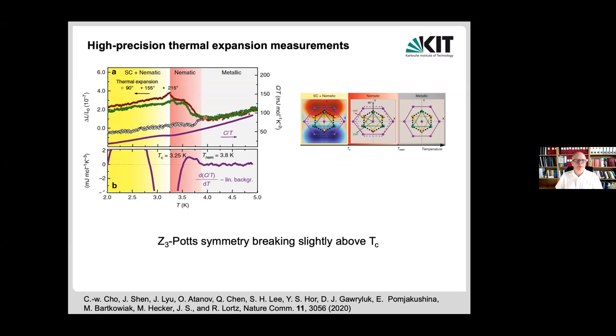What I find simply amazing is if you look at the numbers. The relative length changes that are being measured here are 10 to the minus 7. So if you take the typical size of the unit cell, the length changes induced by those superconducting fluctuations are of the order of a fraction of a femtometer, so a fraction of the size of the proton. Of course, this can be resolved because you ultimately accumulate over the sample size, but it also tells that there's a tiny structural response to that system that breaks this rotational symmetry.